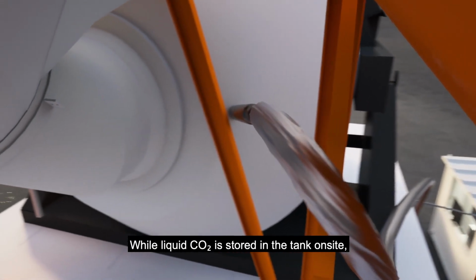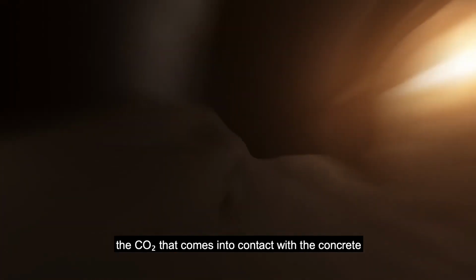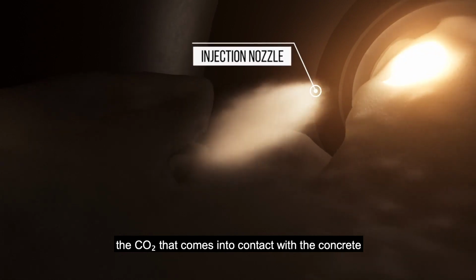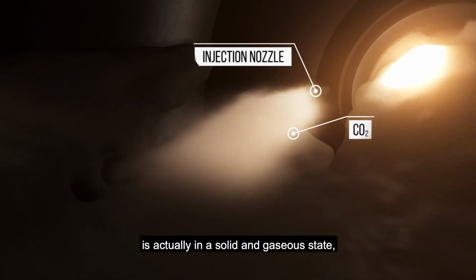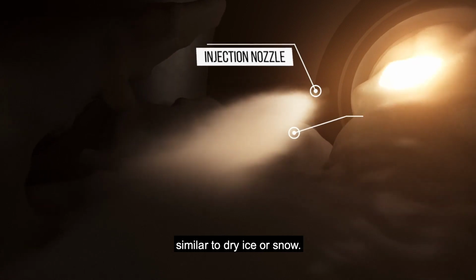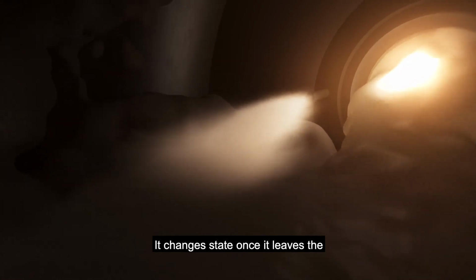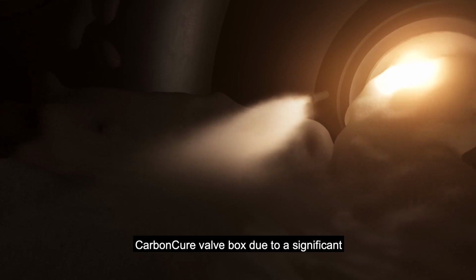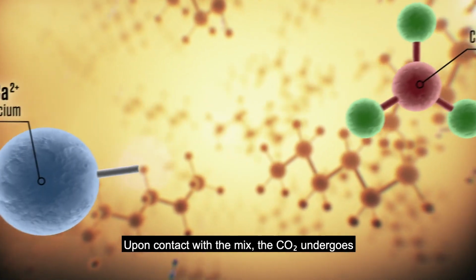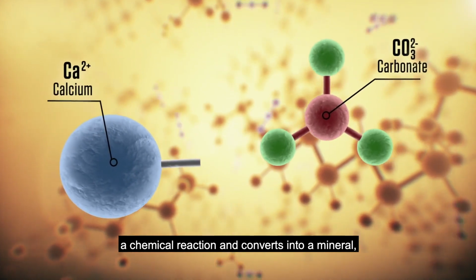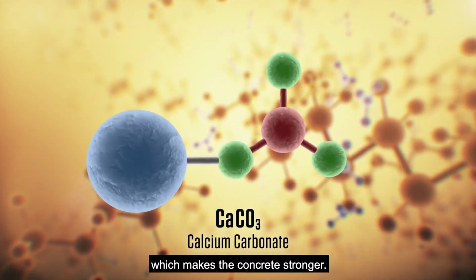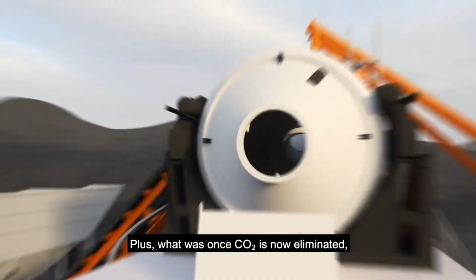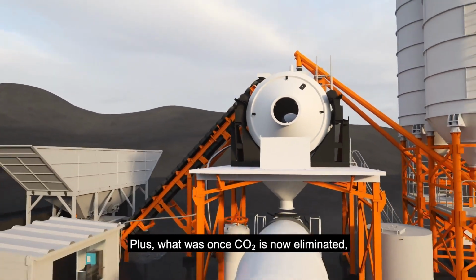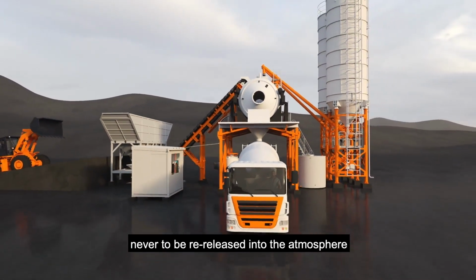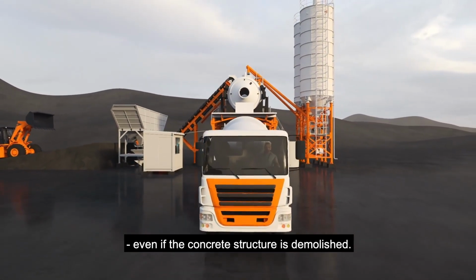While liquid CO2 is stored in the tank on site, the CO2 that comes into contact with the concrete is actually in a solid and gaseous state, similar to dry ice or snow. It changes state once it leaves the CarbonCure valve box due to a significant drop in pressure. Upon contact with the mix, the CO2 undergoes a chemical reaction and converts into a mineral, calcium carbonate, which makes the concrete stronger. Plus, what was once CO2 is now eliminated, never to be re-released into the atmosphere, even if the concrete structure is demolished.